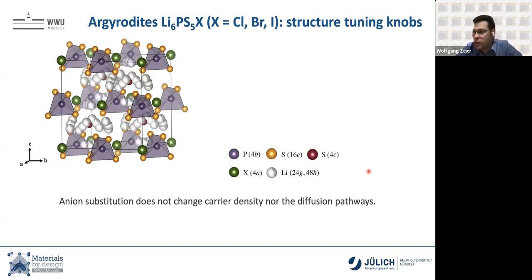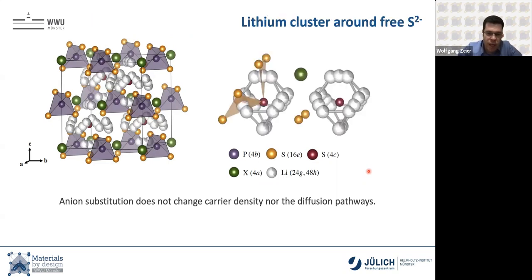And for a long time, we said, well, the lithium is somewhere in there. And this somewhere in there, for us, always was some sort of lithium cage that forms around the sulfur anion. So the jumps that you can have are lithium jumping from here to here, and it can jump back, and that doesn't give you much. It can jump from one of these so-called doublets to another one, and they can fast rotate around their cages, and this is what they do. But long-range ionic transport means we need to jump from one of these cages to the next one. And by doing that, it needs to bypass a halide. This halide will become important.